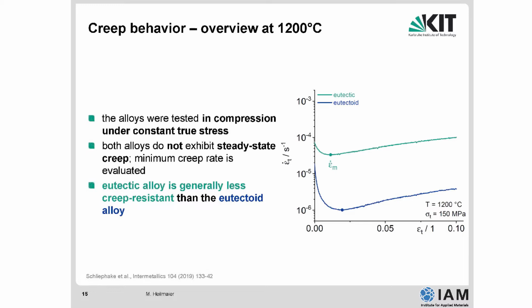What is plotted here? Here you see a creep curve for a constant stress of 150 megapascal. This is approximately the stress a turbine blade in an aero engine would see at start of and landing events when you need the full power of the engine. Of course, when you cruise at high altitude, you need much lower stresses because then you don't run at full revolutions yet. Okay, at 1200 degrees Celsius. And then you see that we plotted here the creep rate, meaning the rate of extension, plastic deformation of the sample with respect to time or strain. Here I plotted the strain.